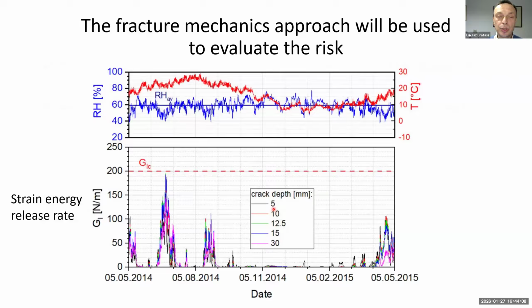So what the user will obtain is the information about the possible crack propagation and crack development in the sculpture, and the fracture mechanics approach would be used, and the user will obtain the information about a parameter which is called strain energy release rate. If the strain energy release rate reaches the critical value for the material, like for the lime wood, which is 200 newtons per meter, then the cracking will happen.